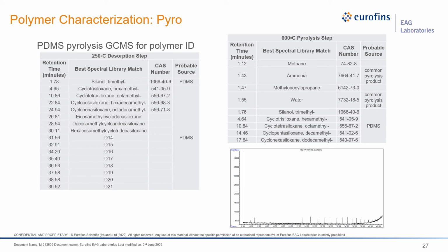What we detect are a bunch of different siloxane-related species, which again is consistent with the presence of PDMS that we are able to detect by FTIR. The second step is the pyrolysis step. This heats the sample at a higher temperature, at 600 degrees C. At this temperature, most organic components tend to break down and decompose into smaller products known as pyrolysis products. Pyrolysis data interpretation can be challenging considering that the molecules you're detecting may not actually be present in the polymer that you're looking at. So looking at reference spectra in literature is a must.